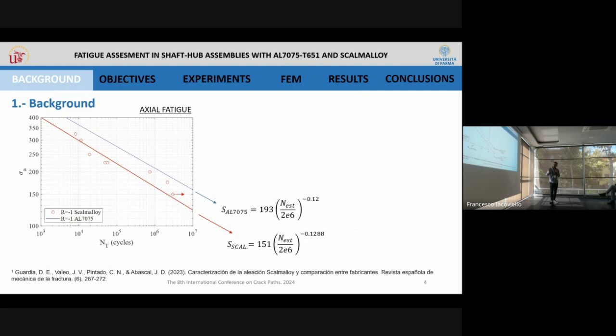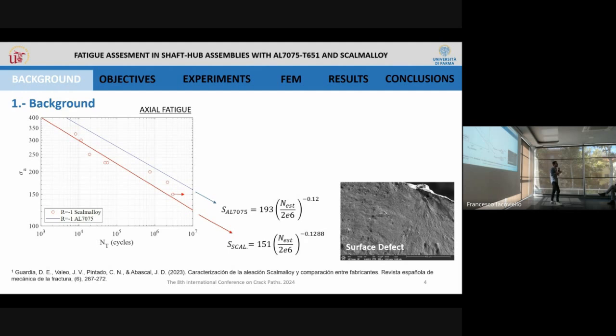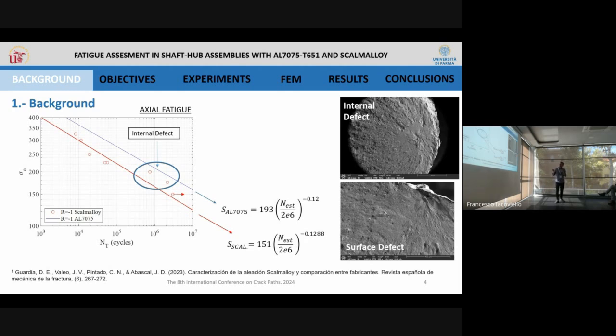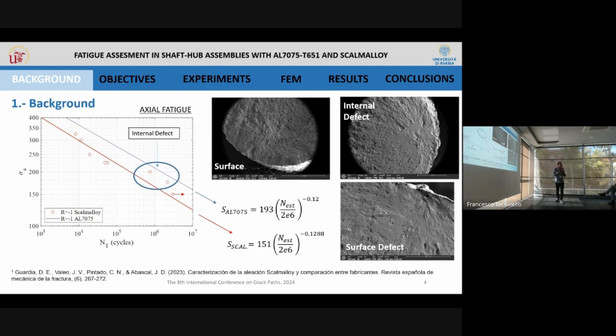In any case, this curve, the Scalmalloy fatigue curve, deserves some more comments, as after doing the tests, we analyzed the fracture surfaces to see what type of defects provoke the initiation of the crack. Something like what Reza showed this morning. You can find surface defects, that are defects very close to the surface, and this is an initiation point. We also have internal defects, that are defects or voids inside the specimen. These defects normally appear for large lives. And also we have full surface initiation, which is the typical initiation that we can find, for example, in aluminum 7075, a crack that initiates from the surface.